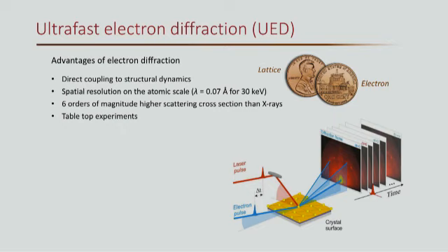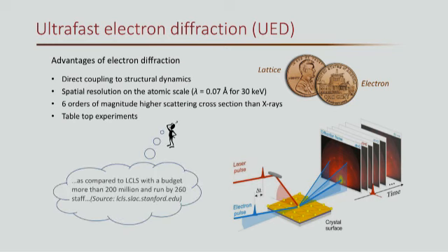So there are several advantages of doing electron diffraction. I won't go through every one of them, but basically the idea is, compared to its close counterpart of, say, X-ray diffraction, electron diffraction has much higher cross sections, so you don't have to wait for like 10 hours to get the same amount of signal from non-resonant X-ray diffraction. For resonant X-ray diffraction, it's a different story. And of course, compared to X-ray diffraction, where you can also get this kind of structural information, UED is usually a much more compact setup that you can actually build in a lab, instead of, say, going to some beamline facility where you, for example, use a free electron laser to create an X-ray source to do time-resolved X-ray studies.